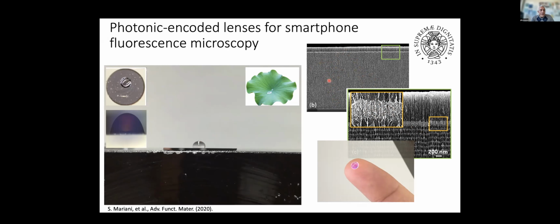So the nice thing here is that after you form this lens, you can etch away the porous silicon around the drop, because everything is passivated, protected by the silicon. And then when you peel the lens out of the silicon chip, you get the lens with the optical filter integrated in it. So in this way, you can easily fabricate a magnification lens which has an optical filter integrated in it.